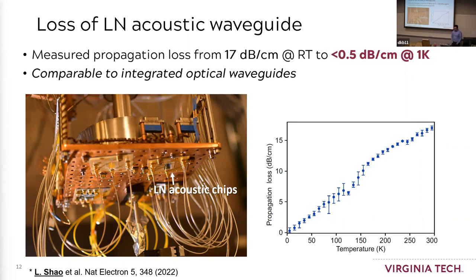And as we cool our device down from room temperature at 300 K to 1 Kelvin, we can see the acoustic loss actually gets eliminated. And at this 1 Kelvin, what we measure is less than 0.5 dB per centimeter. And we're actually not resolving better than 0.5 dB. That's just due to the measurements we're doing. We're not making a cavity here. We're just making two acoustic devices with different lengths, and comparing the propagation loss between them. So that's the conclusion we get. It's a pretty good one, because the performance is really good.